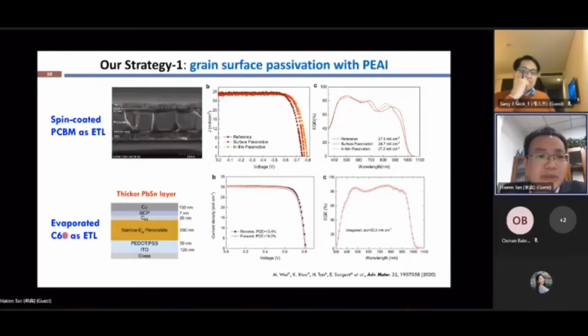And later we use carbon 60 evaporated as the electron transport layer, so we can use a thicker absorber layer, but still limited by the diffusion length of this material. So we can only use thickness up to 650 nanometers. In this way, we can further increase the JSC value of the devices, and the efficiency becomes 19%.